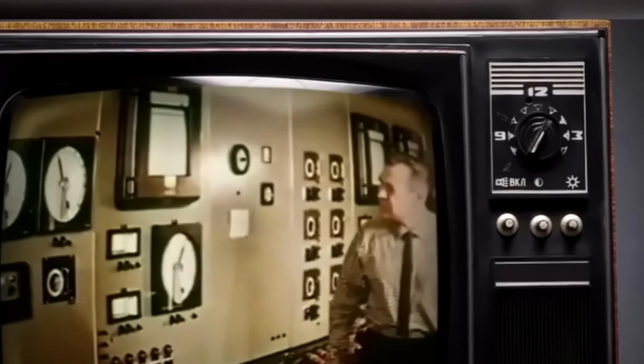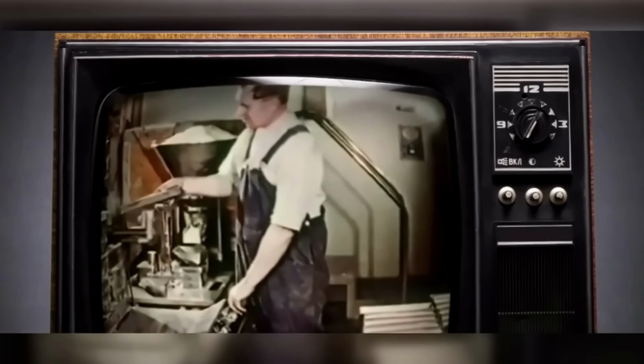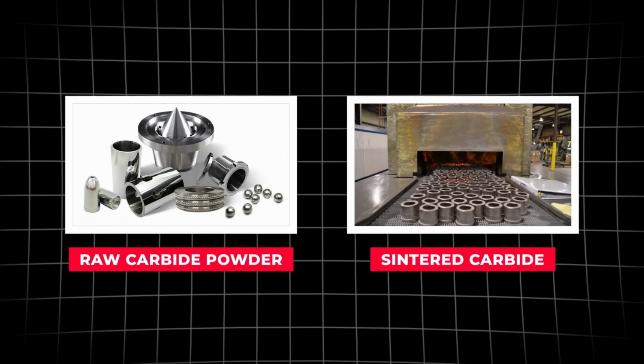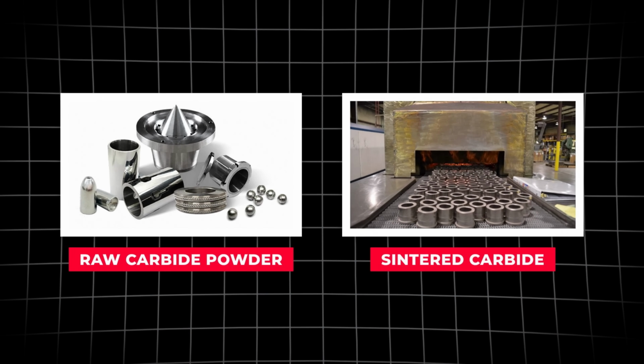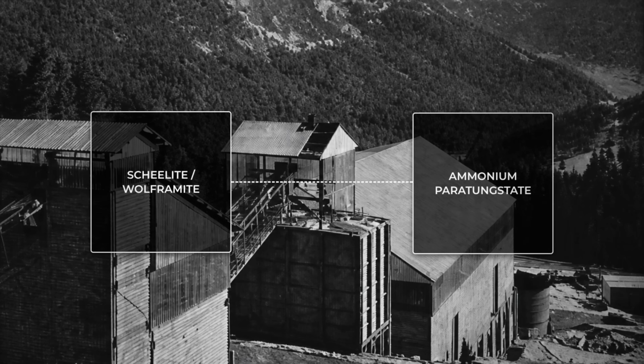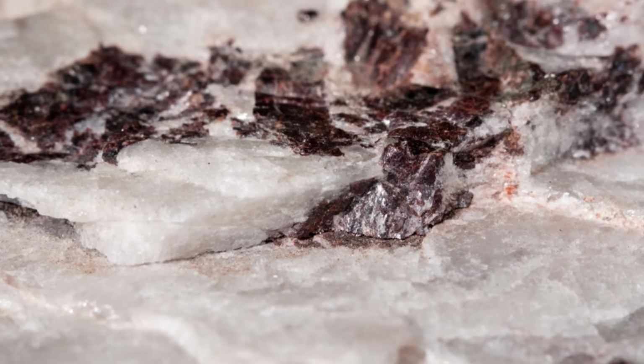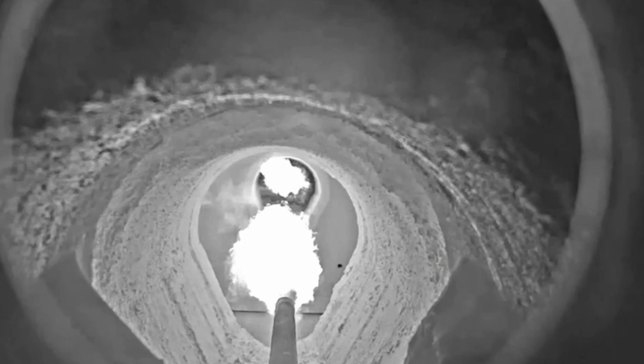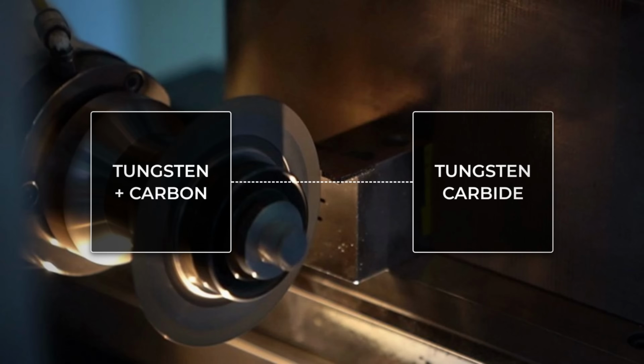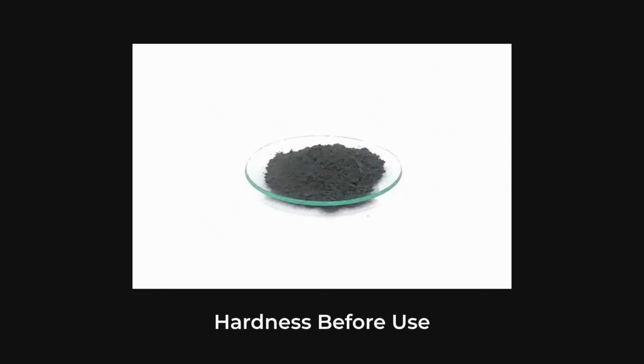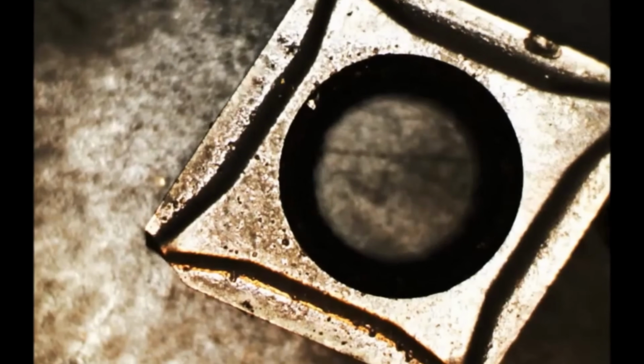What Haglund's division was actually doing on that shop floor is worth slowing down for, because the process has barely changed in 80 years, and it is nothing like conventional metalworking. You start with tungsten ore, usually scheelite or wolframite, and chemically process it into ammonium paratungstate, a white crystalline salt. That gets converted to tungsten oxide, then reduced with hydrogen into gray tungsten metal powder. The powder is mixed with carbon and fired, which carburizes it into tungsten carbide. Now you have a black powder harder than almost anything in the natural world, and completely useless, because you cannot cast it, forge it, or machine it.